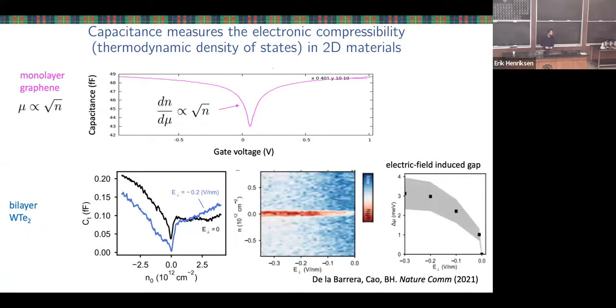You're doing the measurement that would see that. But yeah, it's small. It's pretty hard to measure gaps of the order of a few millivolts. That's actually why the capacitance technique has become useful for things like fractional quantum Hall states. It's certainly hard to measure millivolt gaps using transport if you want to do some sort of activation. But here you can sit at a fixed temperature and just measure the capacitance and therefore the compressibility, and you can deduce the size of a millivolt gap.